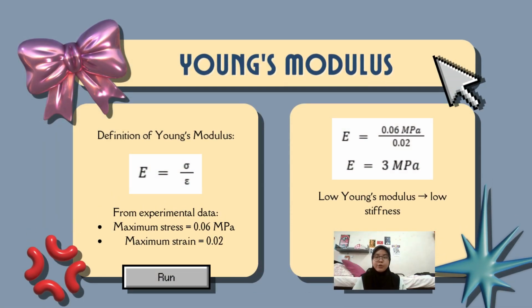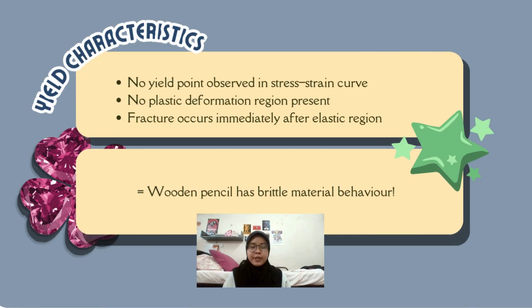So next is Young's modulus, which represents the stiffness of the material. From our experiment data, the maximum stress was 0.06 megapascal and the maximum strain was 0.02. Using the formula E equals stress over strain, we calculated the Young's modulus to be 3 megapascal. This low value indicates that the wooden pencil has low stiffness, which explains why we observe noticeable deflection even under small loads. In terms of yield behavior, no yield point was observed in our graph.